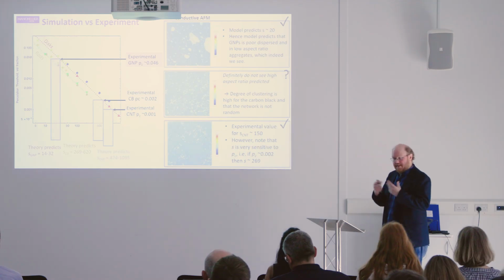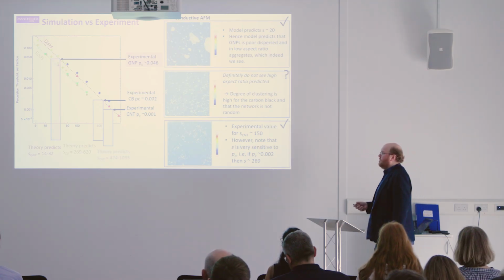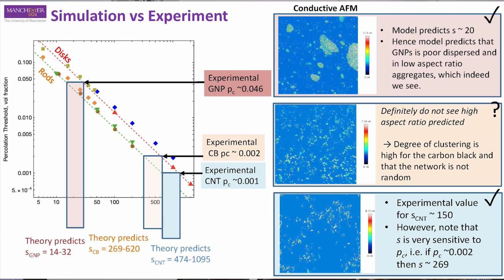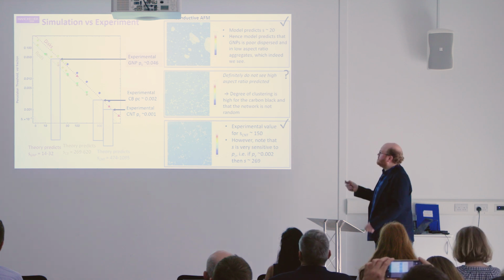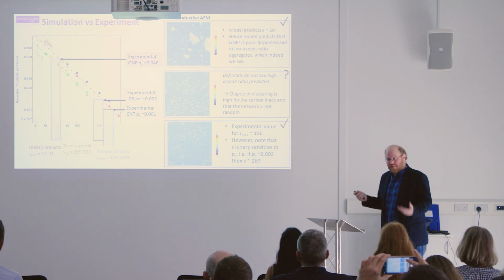We also did some theory, some modeling of these, based on what the predicted aspect ratio should be at the percolation threshold. And you find that for the GNPs, theory predicts the aspect ratio should be around 14 to 30. And that's roughly what we're finding. The model predicts that there's going to be a lot of agglomeration, and that's exactly what we see.